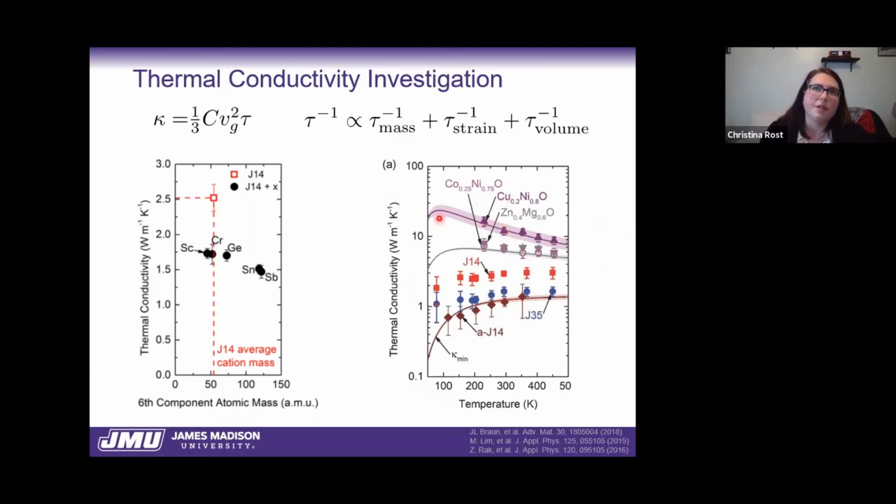So at first, the VCA model didn't exactly work, but the addition of another order parameter that compensated for what we consider the interatomic force constants based on changes in cation oxidation state helped us match this model a lot better. And what we found was that the best fit VCA models revealed that this interatomic force constant disorder scattering leads to this level of reduction.